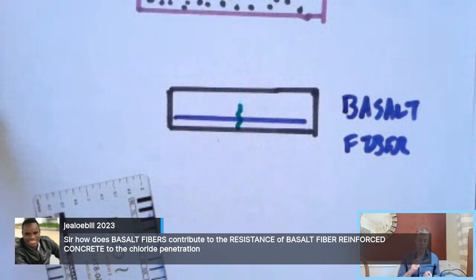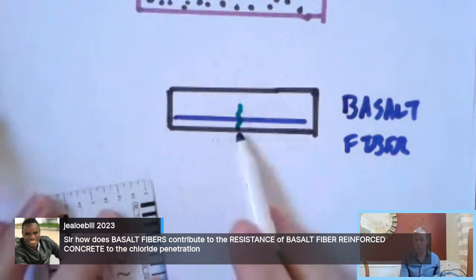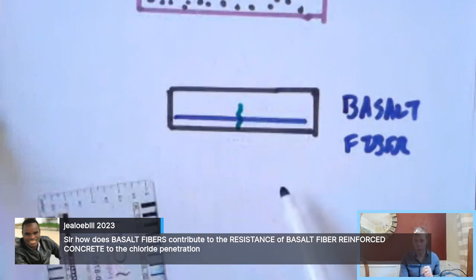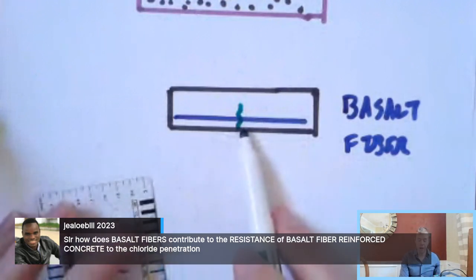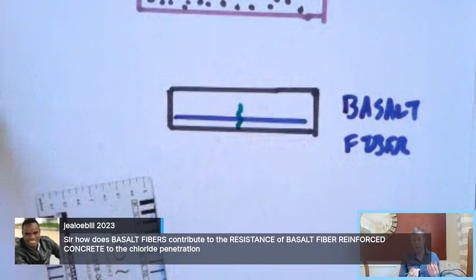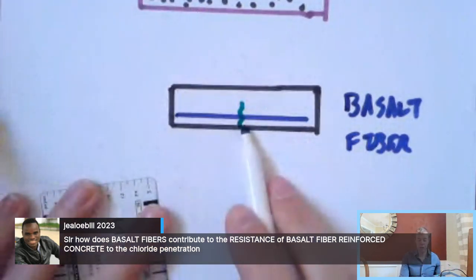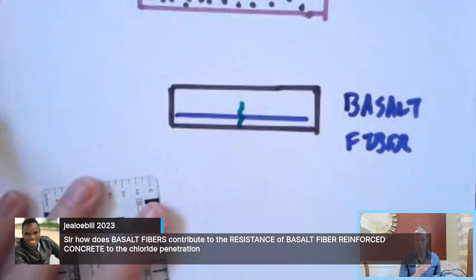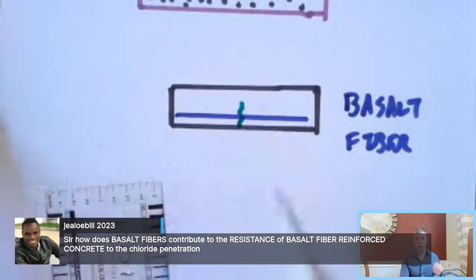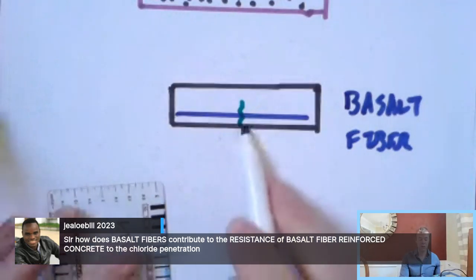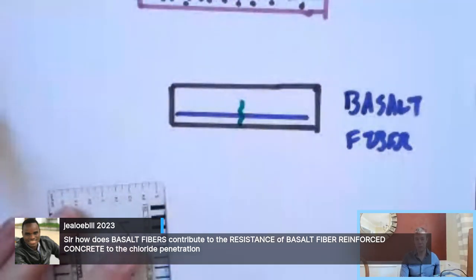One, they're not as stiff as steel is, and so your cracks are going to be larger. How much larger? About double, about twice as large. And they're expensive, but then they say, oh, but they're stronger. Yeah, that's true. But if you care about keeping cracks small, then you're going to need to use quite a bit of the material. There's also concerns about creep and about fire with these systems. And so they haven't seen widespread use in a lot of structural applications.